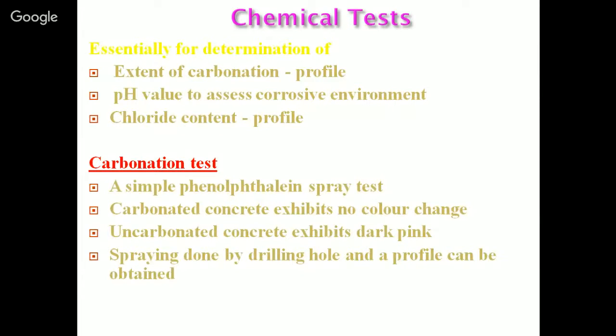Concrete is an alkaline material, its alkalinity is very high, and once carbonation starts its alkalinity goes down, and once alkalinity goes down, the corrosion process starts. So that is related to corrosion. We have to see it from that point of view. So it is very important to determine the extent of carbonation using the carbonation test.